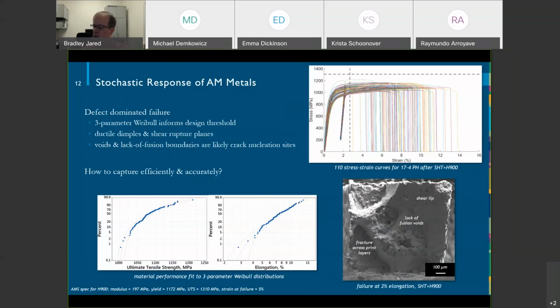We've done work with Weibull distributions, which are very common in even the casting industry and also ceramics, where you start thinking about, well, if I get enough samples, I can establish some sort of probability threshold at which this material can perform. And so now that can inform how you make decisions in terms of design, right? And so again, part of the question is how do we get this data quickly and fast? And that's what a lot of the work we've been doing. But this is, again, quite a bit of uncertainty. If you look at the wrought material here, the strain to failure range is maybe 1%, and we've got almost an order of magnitude higher than that here, right? So there's a challenge there.